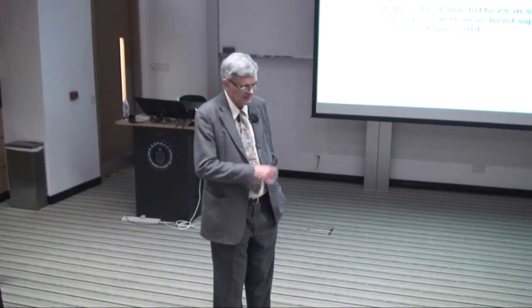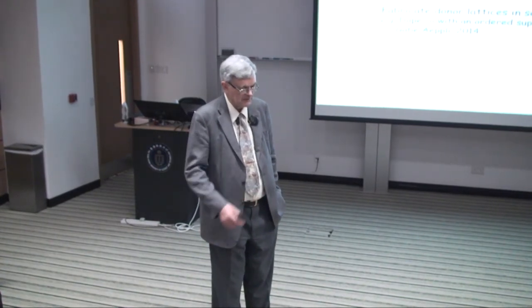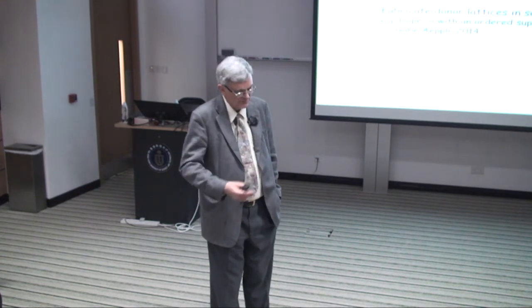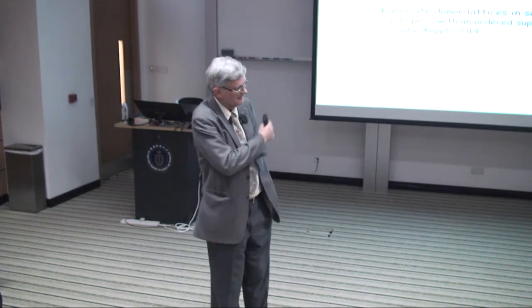Actually, as it turns out, and it's not fully understood, but as I mentioned earlier, a number of the cuprates are quite disordered. This Bisco, which is a cuprate with a maximum TC of 90 Kelvin, 2-layer Bisco, is a very dirty material. But because we're dealing with strong coupling, it survives. In weak coupling, there's analysis going back a long time showing that this type of state shouldn't survive, but it does survive. So it seems to be more impervious to this disorder.